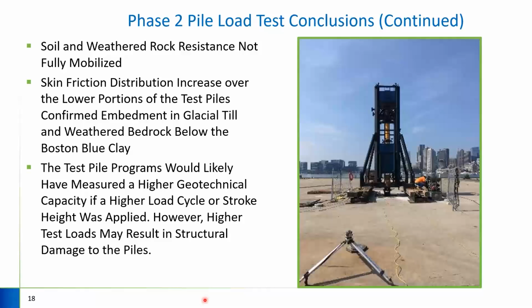So getting into the final conclusions, the soil and weathered rock resistance were not fully mobilized, as we can see through the PDA data. When we looked at the PDA data, as you would assume with the Boston blue clay, it did not have a significant contribution to the actual pile capacity, and these piles were likely driven both into the glacial till and through into the weathered bedrock due to their low pile sets. One other main component here would be that if we did end up testing these piles to a higher load cycle for the rapid load test or a higher stroke height for the dynamic load test, we would see significantly higher loads. But for a project like this, and other projects, you may end up seeing capacities that are limited by your structural design and not your geotechnical capacity.